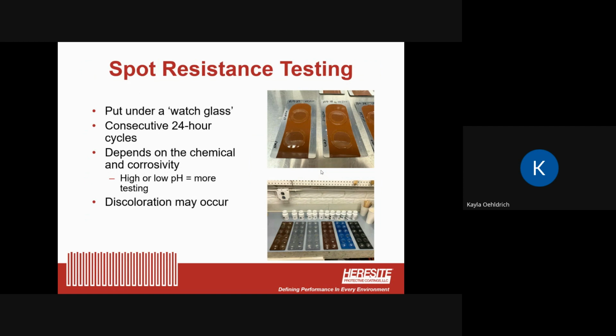Spot resistance testing is what we probably spend the most time doing. We have a cured paint film, and in this one you can see on the top it's our P413, and on the bottom it's our air dry coatings and some of our competitors. So it's put under what's called a watch glass, and you can see that at the top. It's a piece of glass where the solvent is put underneath.